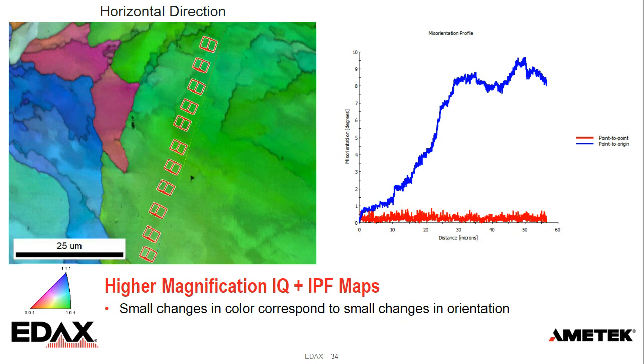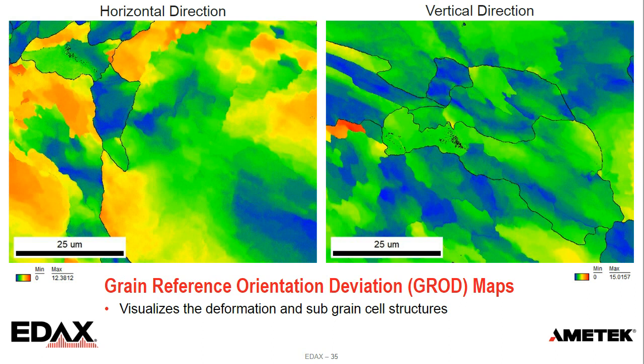And we can visualize that with other types of maps. One is what we call a GROD, or grain reference orientation deviation map. In this case, we calculate a grain, like we showed earlier. We determine a reference orientation, and there are a number of ways we can do that. Once we have that reference, we can shade each point within the grain by its misorientation from that reference. The black lines I've drawn on there are the determined grain boundaries, so it gives us some idea where the grains are located.